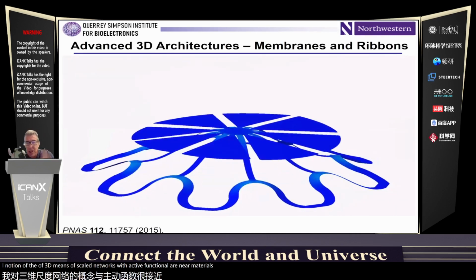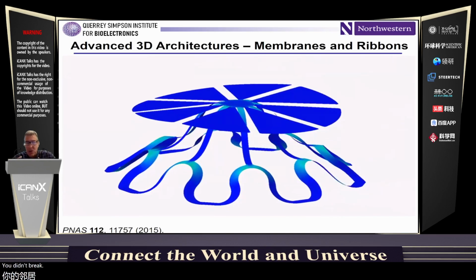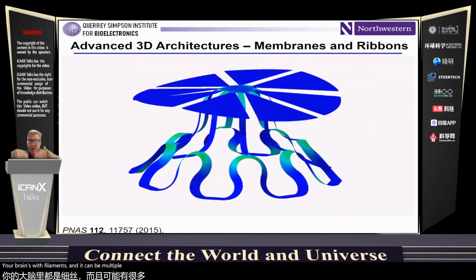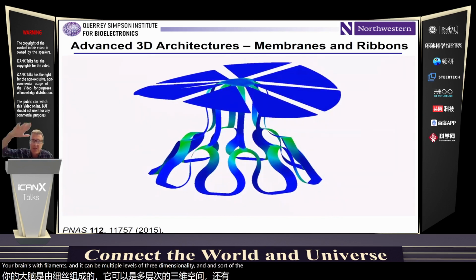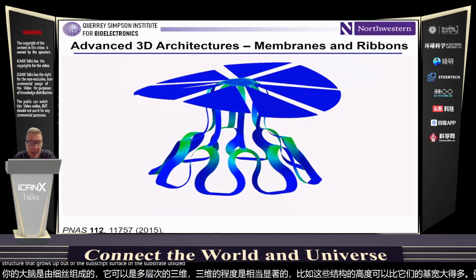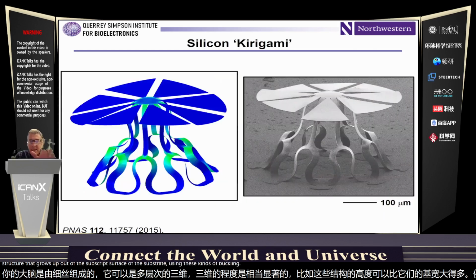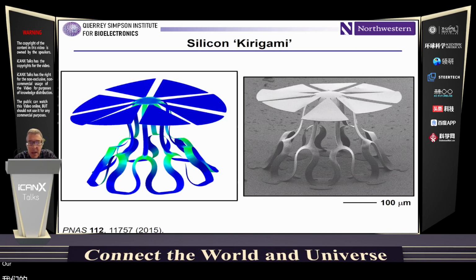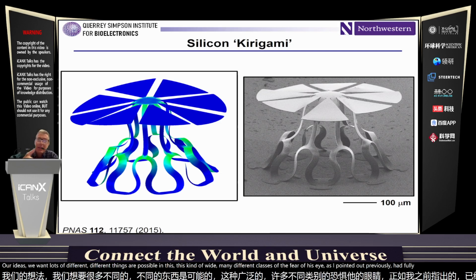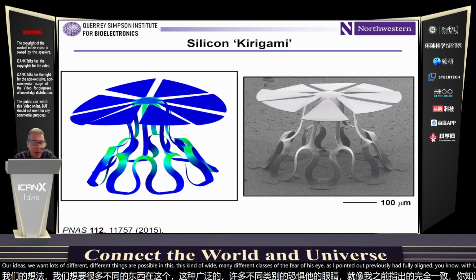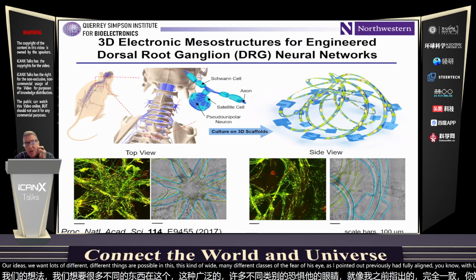It doesn't have to be just filaments. You can combine membranes with filaments, and it can be multiple levels of three-dimensionality, and sort of the extent of 3D can be quite significant. Like the heights of these structures can be much larger than their base widths. For example, this is kind of a sunflower type structure that grows up out of the surface of the substrate using these kinds of buckling ideas. So lots of different things are possible, and this can apply to many different classes of materials, as I pointed out previously, and fully aligned with microsystems manufacturing approaches that have been developed over the last 50 years in industry, which is important.